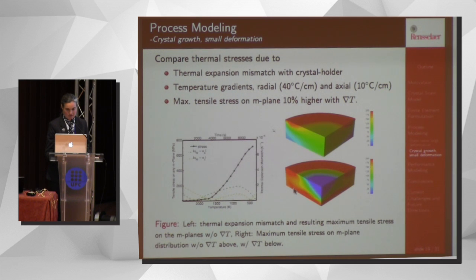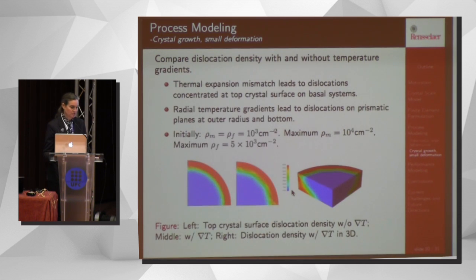But the temperature gradients also have an impact. We can see that we get this very high tensile stress on the M planes on the top of the crystal near the edges due to that thermal expansion mismatch. But when we have temperature gradients, we also see high stresses on the bottom of the crystal as well. And that correlates with the cleavage that they see. We also looked at the dislocation density, and what we found was that the radial temperature gradient leads to dislocations on the prismatic planes at the outer radius and at the bottom. And the thermal expansion mismatch, as one might expect, leads to dislocation concentration at the top crystal surface on the basal planes.